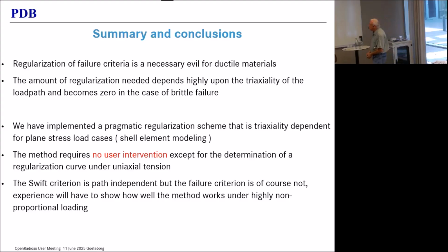It's not disputable. The amount of regularization that you need depends highly on the triaxiality of the load path, and in the case of brittle failure, for instance, pure shear under quasi-static conditions, it becomes 0. We've implemented something very pragmatic that is triaxiality dependent. For the moment, it's limited to plane stress. The beauty is it requires no user intervention. You don't have to do anything. All you need to do is get a regularization curve for uniaxial tension. So there is no additional work to what you already do.